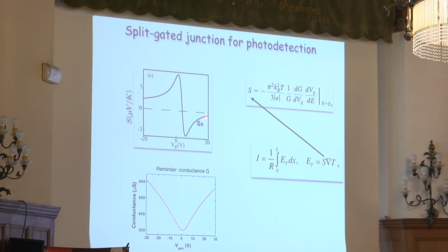For graphene, the Seebeck is a little bit wild. It goes up, then down again, changes sign, and then up again. So it's non-monotonic, which leads to some interesting behavior. But for the nanoscopy, you don't care too much about this. The only thing is that you see clearly that at the Dirac point, it changes sign, and we'll see this in our images.